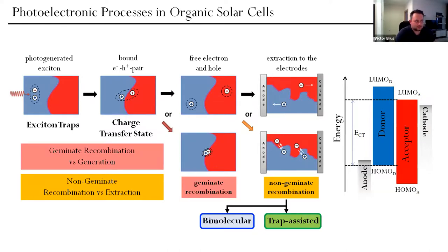of this bulk heterojunction. Why is it called bulk heterojunction? Because we have an interface between donor and acceptor everywhere in the bulk. So it's some self-organized nanostructured morphology of donor and acceptor. And how we make it, we don't control this. So it's self-organized. We make a solution. So we have a solvent, for instance, some chloroform, and put there some donor and acceptor material, dissolve, and then spin coat it on our prepared substrate.